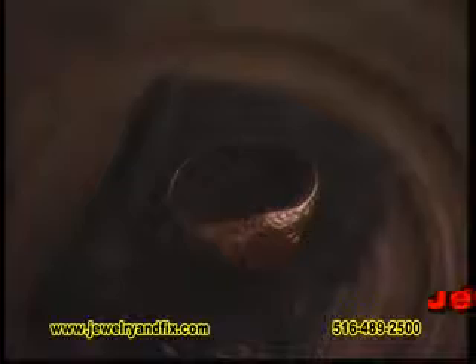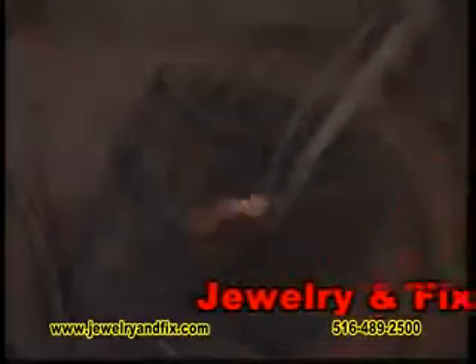Using a soft reducing flame, gently play the flame over the whole piece, heating it evenly until it is a dull red, or about 1200 degrees Fahrenheit. After turning off the torch, quench in water or pickle when the piece loses its color. Quenching keeps the metal in a fine-grained condition.